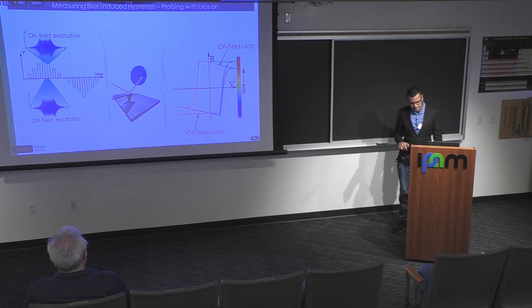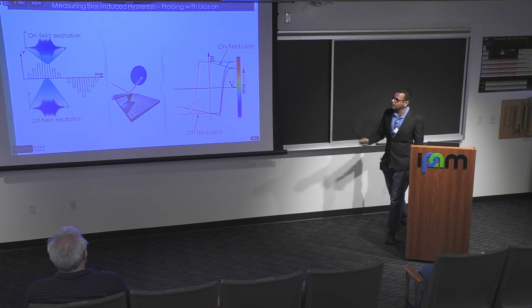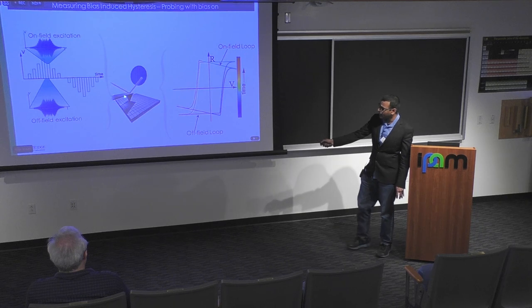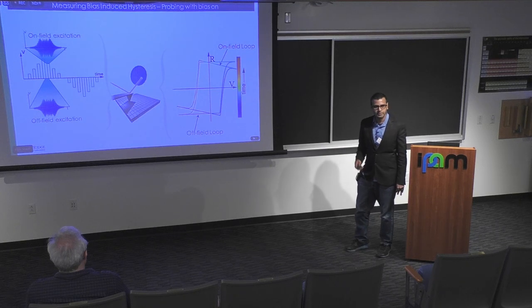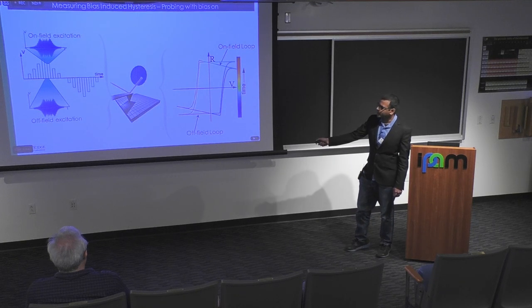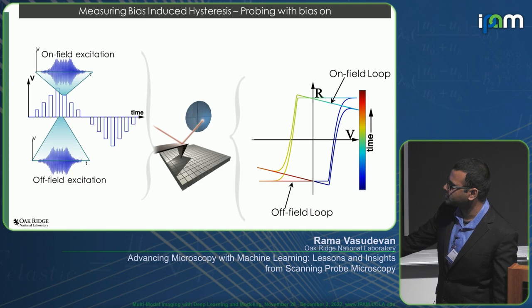And so one of the things that we do often with the scanning probe microscope, at least at the CNMS, is when we want to probe the functional properties of materials like piezoelectric or ferroelectric materials, we can apply these sort of complicated bias waveforms, where these are triangular envelopes of DC pulses that are applied either to the tip or the sample. And so as a function of this bias, we can then have some readout pulses, which will give us the state of the system after application of each of these bias pulses.